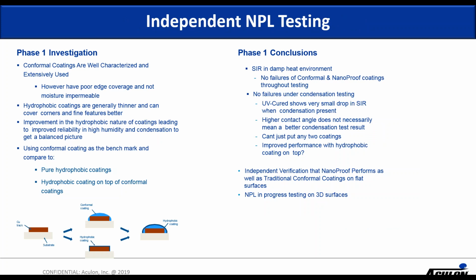So now we're going to get into some independent NPL testing that was recently done at the end of last year. They did a study, again, this is on the IPC multi-purpose test boards, so a study on flat boards, to evaluate the performance of conformal coatings, and they also included several of the NANOPROOF products. And they compared the performance of these coatings as well with the waterproof protection ability of having a hydrophobic coating. And they essentially confirmed our findings, that having an insulating layer, which is what the NANOPROOF series provides, is the most important aspect for providing water protection. Simply having a repellent surface doesn't necessarily protect from current leakage.